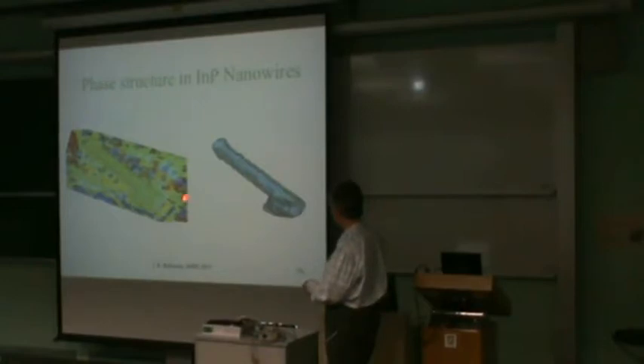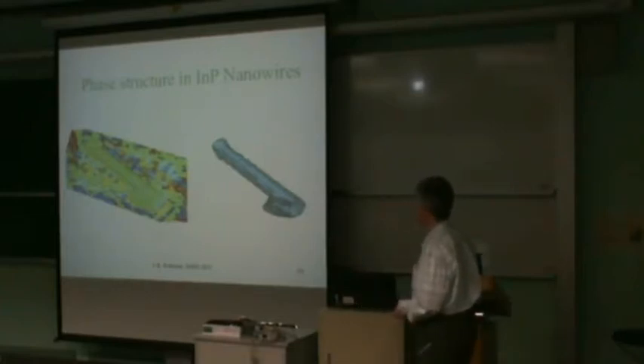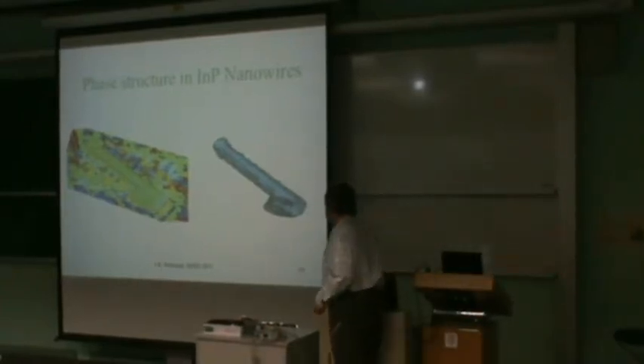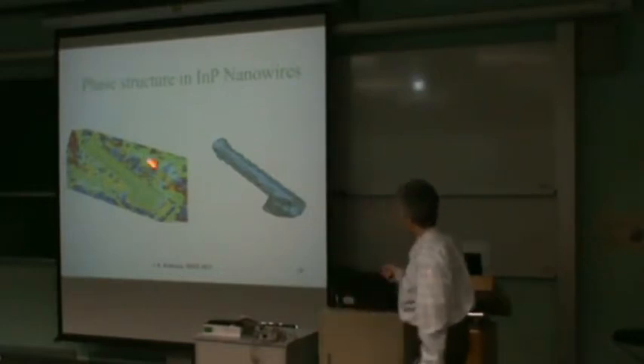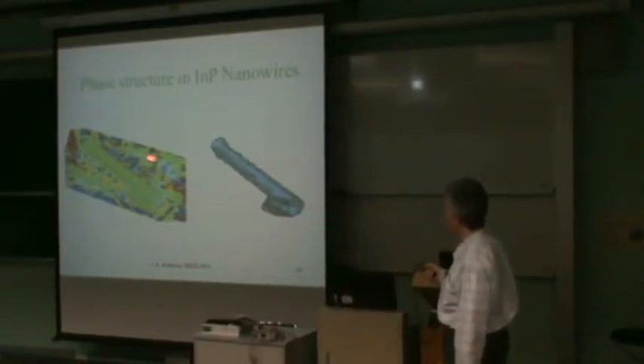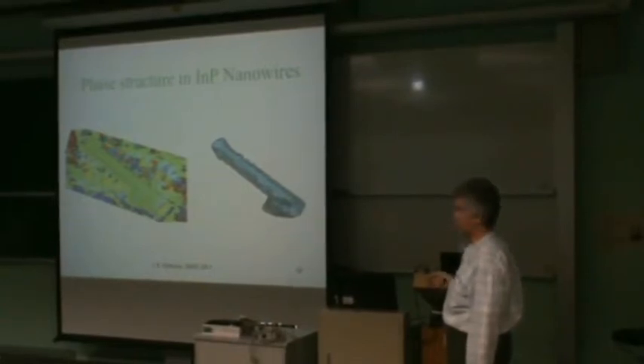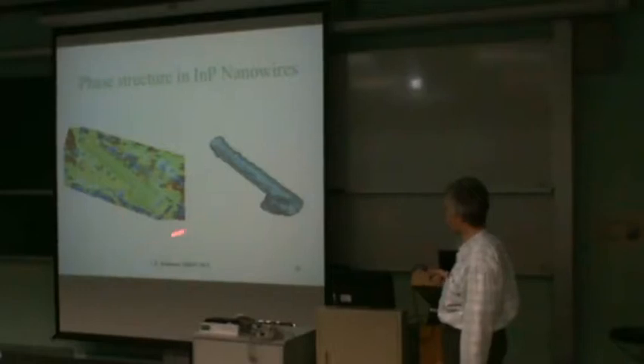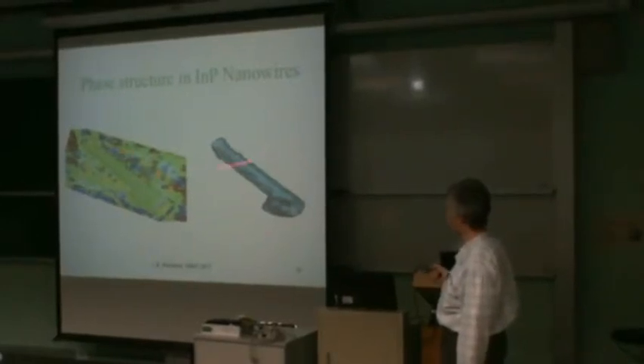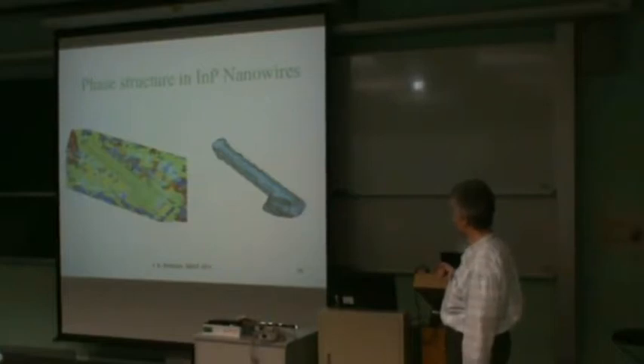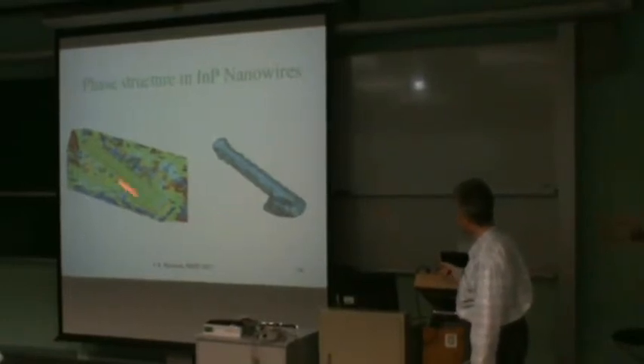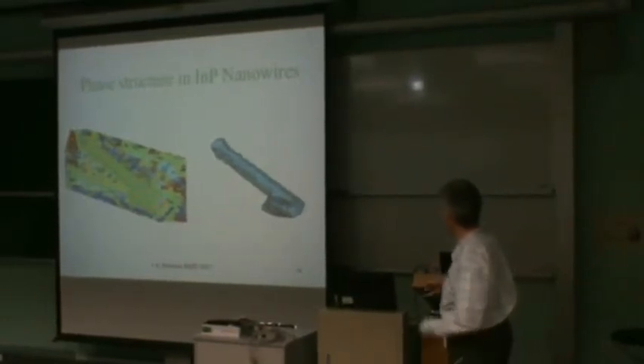But we do get this cross section through the structure, and we're seeing a mapping of the strain inside this nanowire from the coherent diffraction image. By the way, when you look at the images that I'll show, I do this in my head because I've been looking at these for so long, but just please ignore everything outside the wire. This is the phase of a complex number, which is 0. So it's just a random background, and don't be distracted by it. What we're looking at is the phase of the image inside the wire, which is relatively constant with a very slight gradient running along it in that direction.